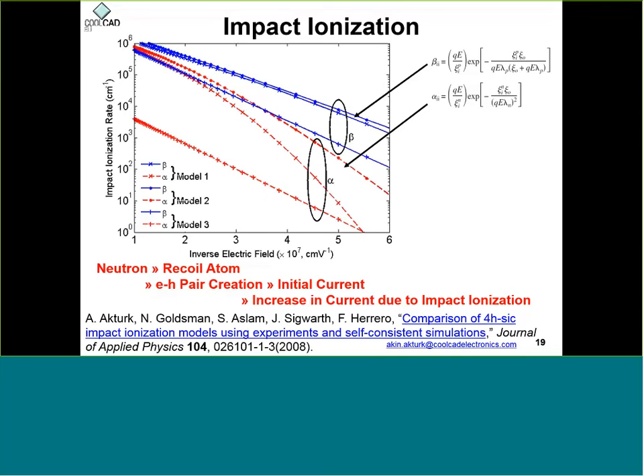So our initial analysis indicates that the neutron is causing a recoil atom, a primary or secondary neutron. Then it creates electron hole pairs along a track. It's about 1 square micron in area and can be several microns in length, and that's in a large field. So then you have this J·E kind of heating, and that heating can be sustained for a long enough time, and that causes a failure. So when you calculate this failure, you shouldn't be using the kappas or the thermal resistances, because these are very short time scales, and they are generally governed by the heat capacity.